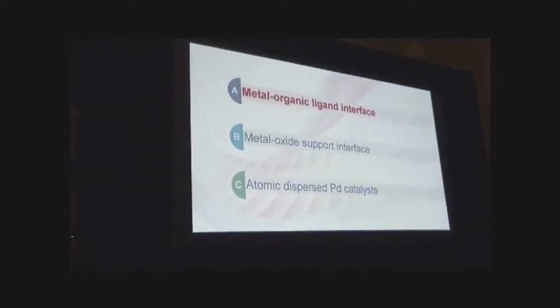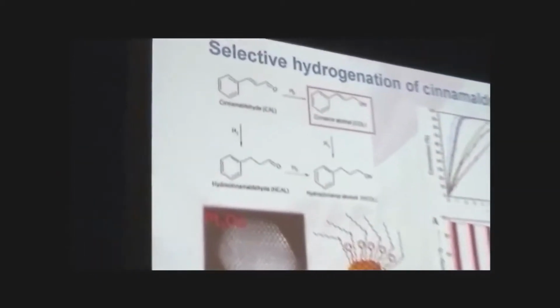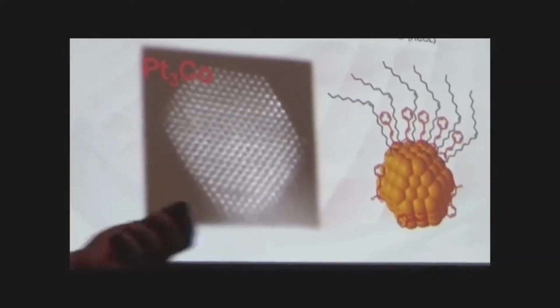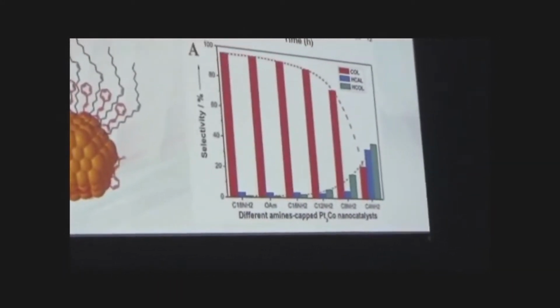My talk consists of three parts. The first part is the metal-organic ligand interface. As I have stated, during synthesis you usually add some organic surfactant to synthesize the unique nanoparticle. And for the catalyst, when you test the catalytic performance, usually you remove the ligand to expose more active sites. But when you keep the organic ligand on the surface, maybe you get some unique selectivity.